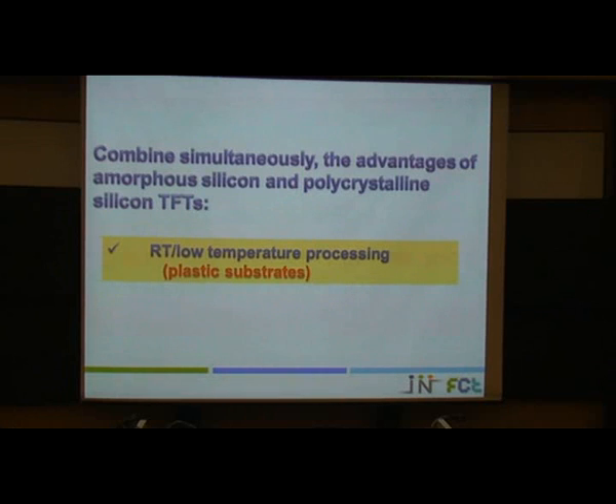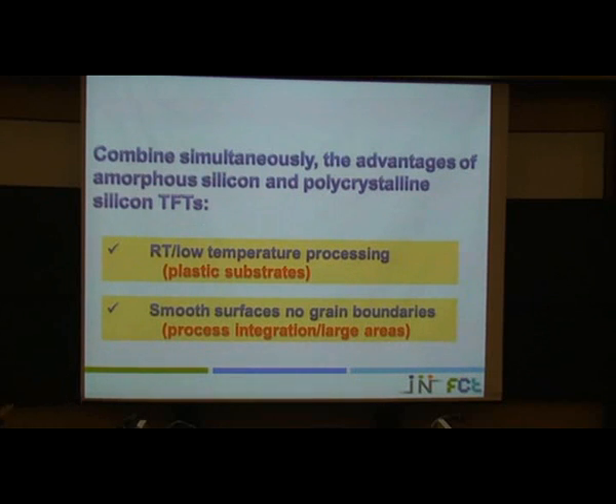First, we can deposit the material at low temperature or even at room temperature, so we are not limited in the substrate that we want to use. And since the material is amorphous, the surfaces are very smooth, which is typical for amorphous materials, so we don't have grain boundaries. For processing, this is a very good advantage, because if I'm processing large areas of 1 meter or 2 meters, it is better to have amorphous materials because they are more homogeneous. If I'm doing a lot of microelectronic processes, etching and so on, I don't have grain boundaries. So the integration on large areas is much easier.